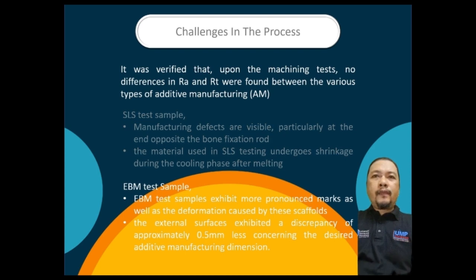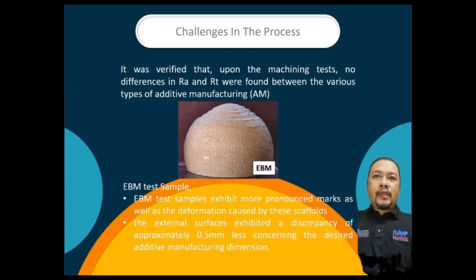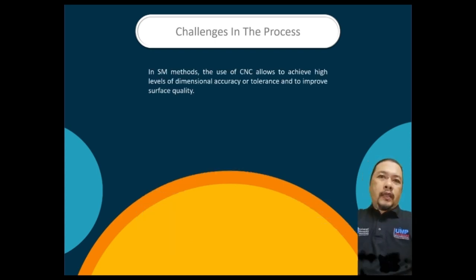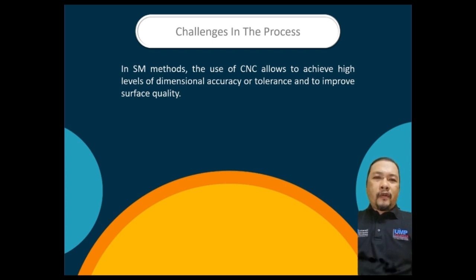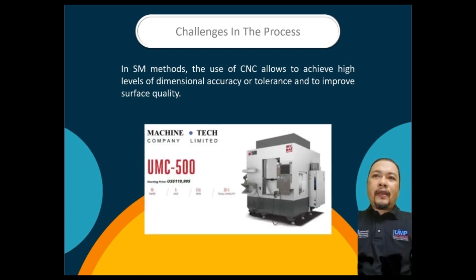For the EBM test sample, it exhibits more pronounced marks as well as deformation caused by these scaffolds. The external surfaces exhibited a discrepancy of approximately 0.5 mm relative to the desired additive manufacturing dimension. In the SM method, the use of CNC allowed achieving a high level of dimensional accuracy or tolerance and improving surface quality.